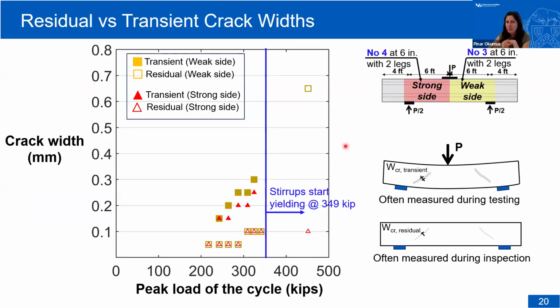This plot is showing the same thing, so residual and transient crack widths this time, but we're plotting them together. So these hollow markers on the bottom are the residual crack widths from both sides. So it's nice and small. This is what you saw in that picture. And then these are the transient ones that we measured through testing. So one very interesting conclusion we make from here is that transient crack widths actually can be 2 to 5 times as high as residual cracks. And that's important again because residual cracks are what we're measuring during inspection. And then once the stirrups yield, the residual crack widths get much larger as well.